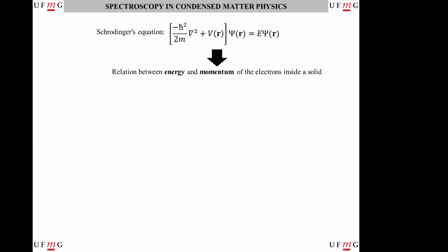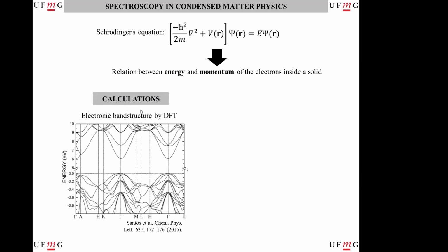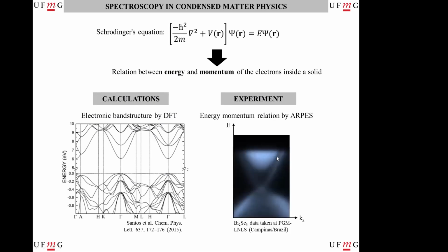First, to give a little review on the subject of spectroscopy, we know that from the Schrödinger equation, we can retrieve the relation between the energy and momentum of the electrons inside the solid. We can use calculations to get this relation. Here there is an example of an electronic band structure calculated with density functional theory of an insulator. But we can also retrieve this relation using experiments that I will explain in a minute. Here's an image of angle-resolved photoemission spectroscopy of Bismuth Selenide taken at the Brazilian synchrotron in Campinas, which is the way to relate the energy-momentum relation from the calculations and experiment.